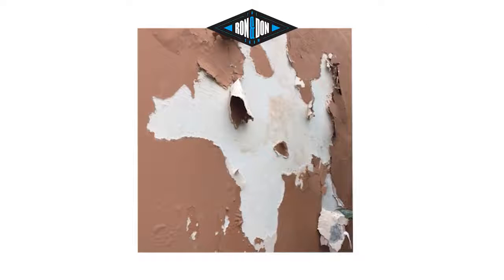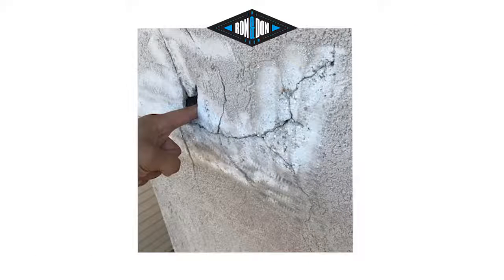I guess that leads right into me, and we had some real major problems in Maine and Maryland and in Austin, Texas, where the whole exterior surface looked like it had the scabies or chicken pox, and it was a mess. Exactly. And we were running into a lot of those same situations, particularly the ones in the northern climates. And while the solution sounds easy, it's actually a little labor intensive, because what you've got to do in that case is find all the delamination on the building, remove it, and then reinstall either a good primer over the top of it to prevent it, or in some cases, we had one or two of them where we actually had to take the entire system off the sections and reapply it again, which gets to be quite labor intensive.